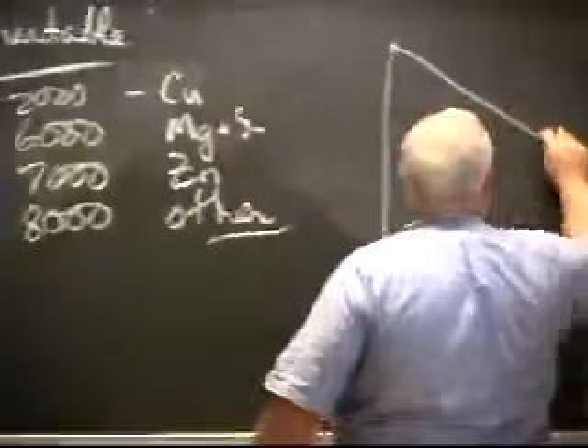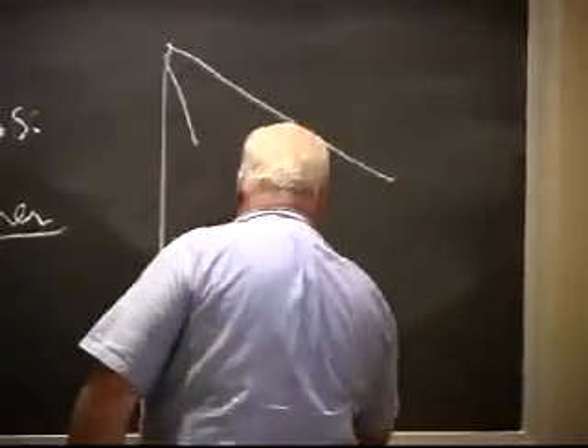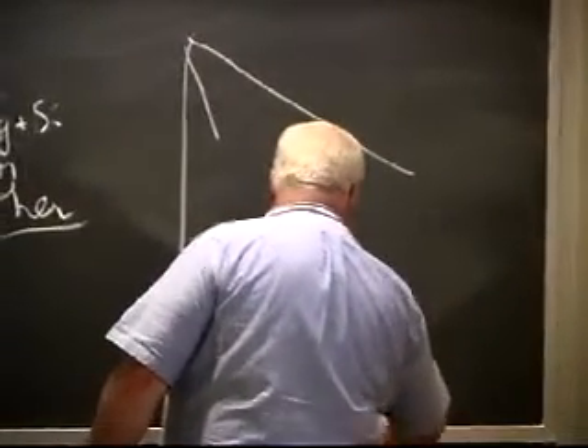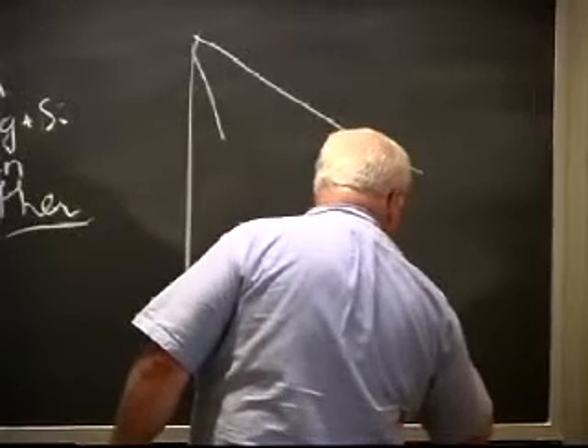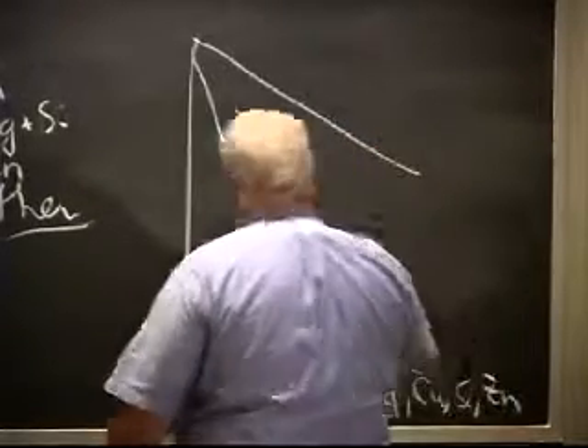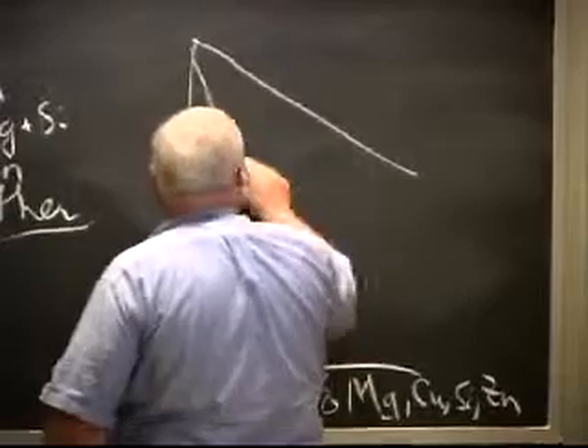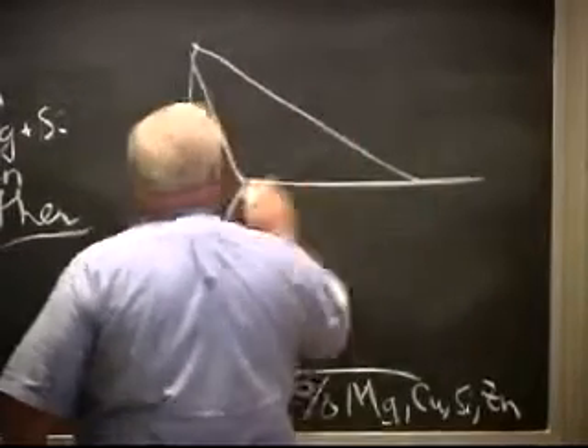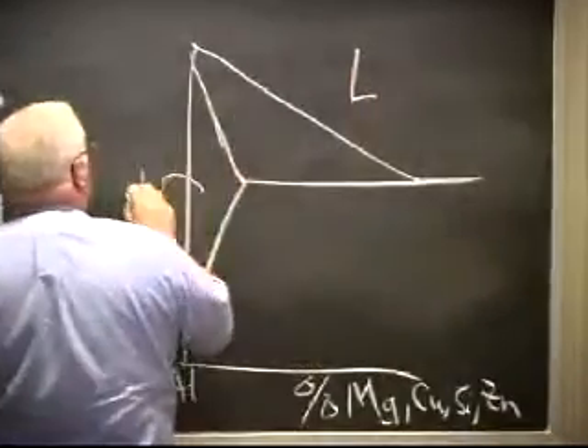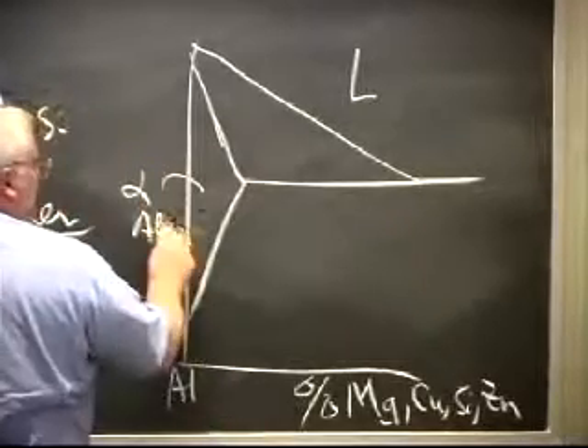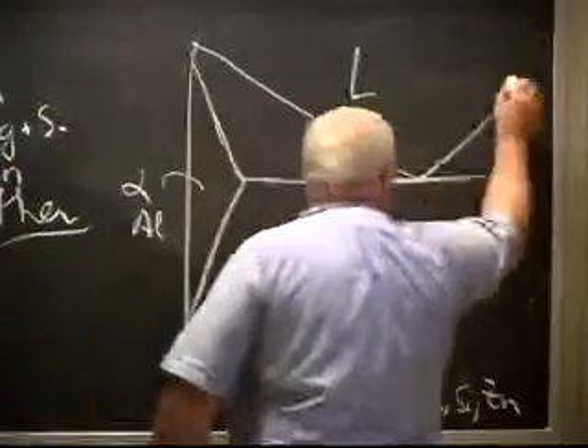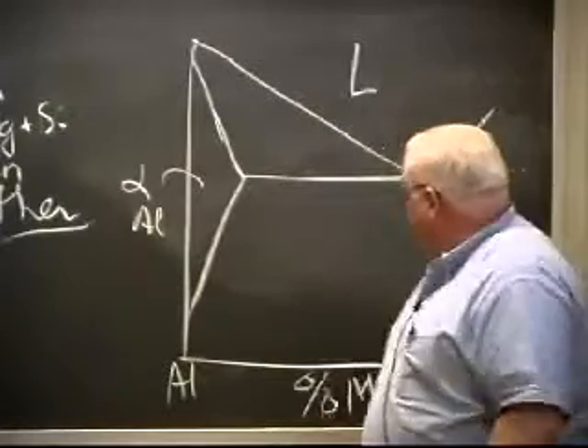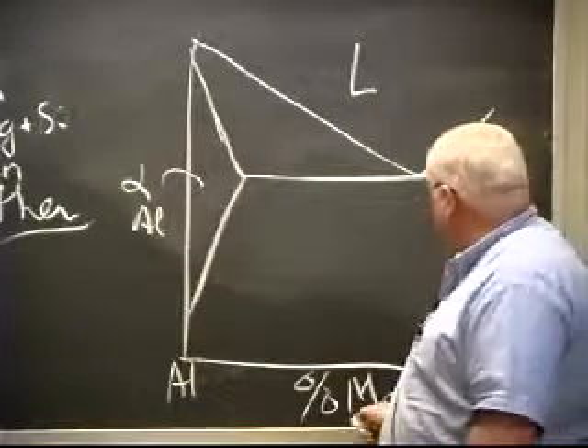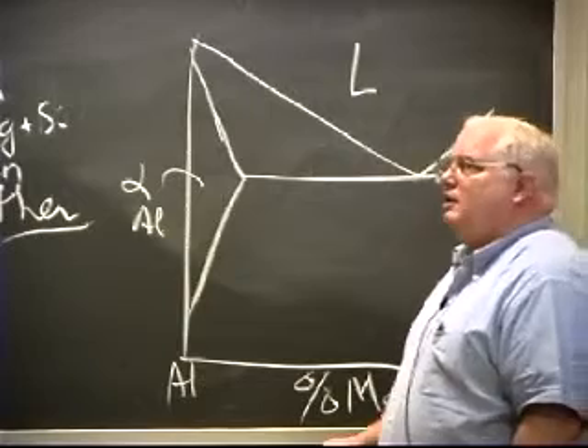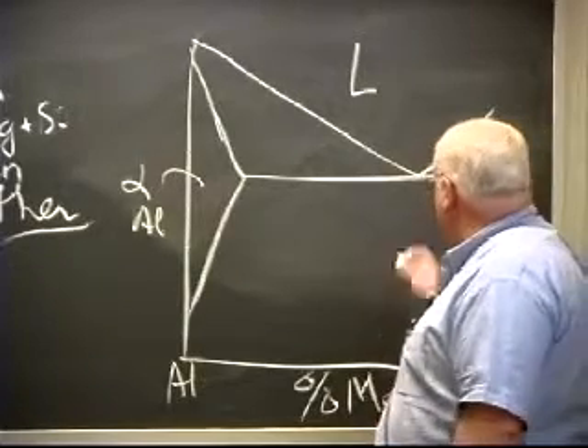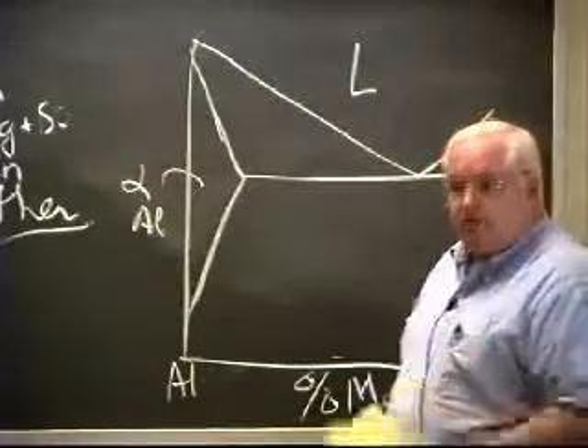Heat treating of aluminum alloys, you typically have a phase diagram where this is the percent magnesium or copper or silicon or zinc. And this is 100% aluminum over on this side. You have a eutectic type of diagram where you have liquid. This will be alpha solid, that's aluminum solution. And you'll have a compound over here. It could be copper 2 aluminum. It can be magnesium 3 aluminum or 2 aluminum. I can't remember exactly. But all these form intermetallics.